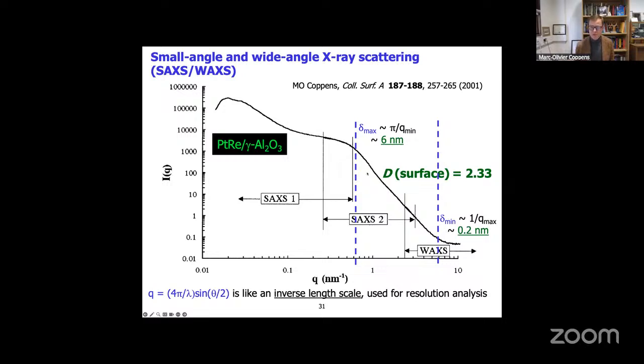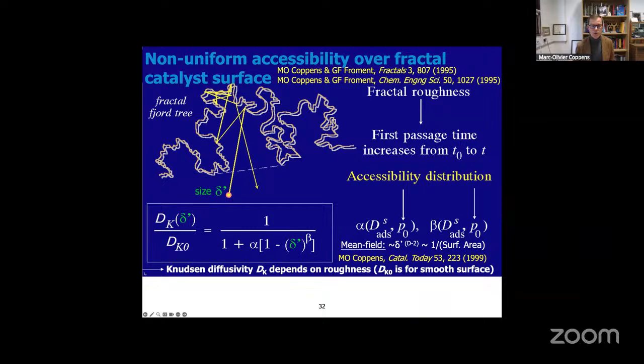So they really are fractally rough, which is not something you can easily see with adsorption experiments, as you have to cover that whole range. And so accounting for this would be important if you're interested in something like catalytic reforming using that type of catalyst. So if you then zoom in, well, a molecule will see this roughness of the surface. And if you are, say, in catalytic reforming, you have gases. And so these gas molecules collide with the pore walls, interact with the pore walls. And so as a result, the first passage time for a molecule to go through a single pore with its rough walls, or through porous material, that first passage time will increase from a T0 if the pores were smooth to T, which is larger than T0 if the pores are rough.